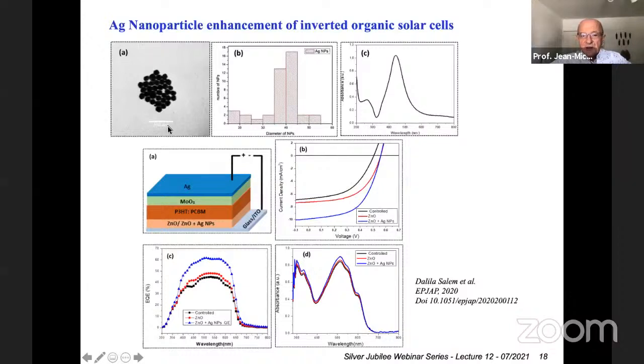And we do not incorporate the nanoparticles into the absorber, because if you incorporate the nanoparticles directly into the absorber without coating them with an insulator, like a silica shell or whatever will insulate them, they will short-circuit the electron hole pair generation, because an electron flying close to a nanoparticle will be spontaneously attracted by the nanoparticle owing to the polarization of the nanoparticle. Then the nanoparticle becoming negatively charged by that electron will strongly attract a positive charge, a hole. And in consequence, they will recombine onto the nanoparticle, which will make a weird photovoltaic response with a large open circuit voltage, but a very small current that is flying through. So it's not very interesting for the photovoltaic effect because it short circuits the electron hole pair generation.